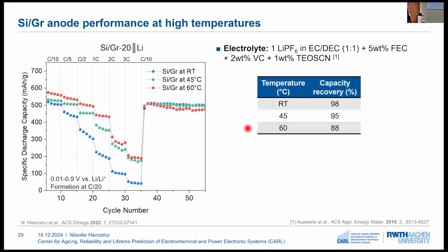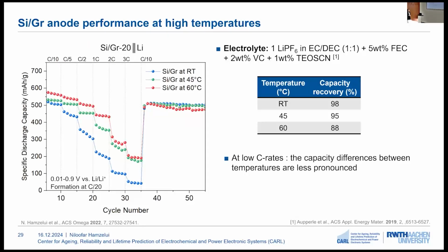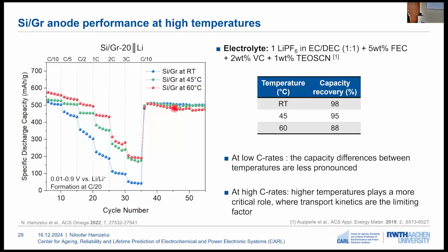If we look at the capacity recovery of the cells, we can see that for room temperature, we have the highest capacity recovery and the lowest capacity recovery for 60 degrees. At low C rates, there is less difference between the capacity at different temperatures, but by increasing the C rate, high temperature plays more of a role in the transport kinetics, and we see more capacity at higher temperatures in the case of the half cells versus lithium metal.